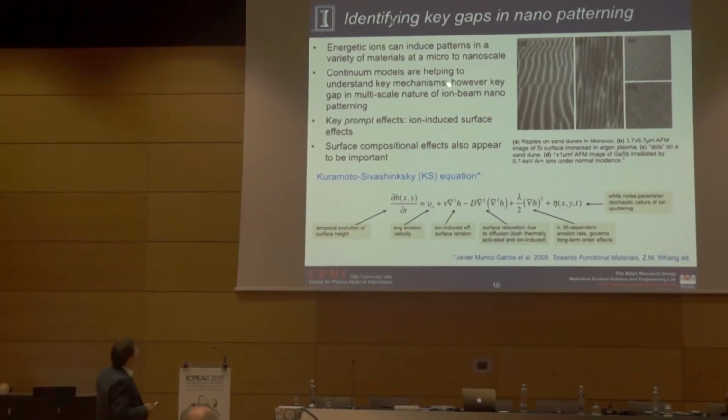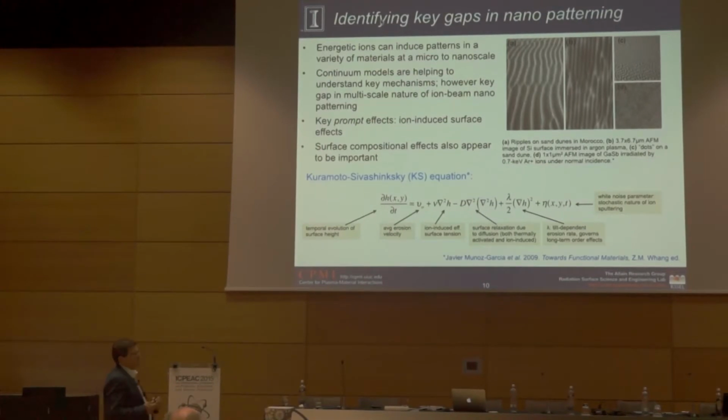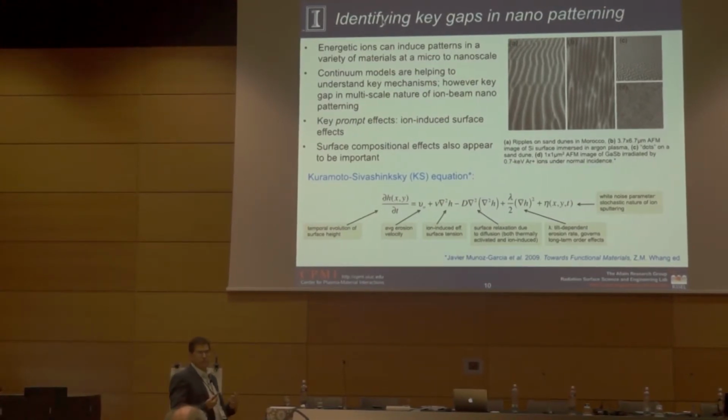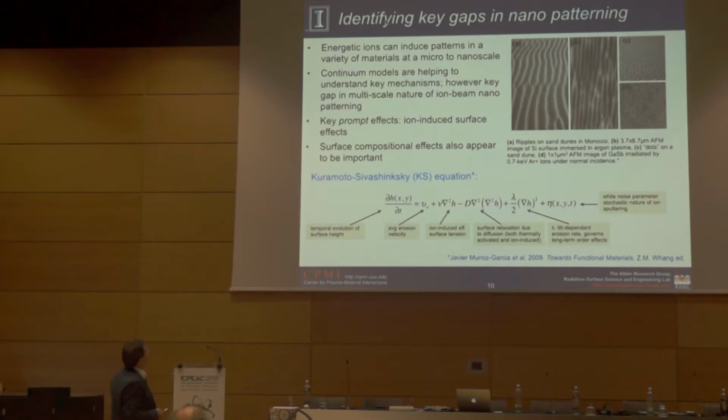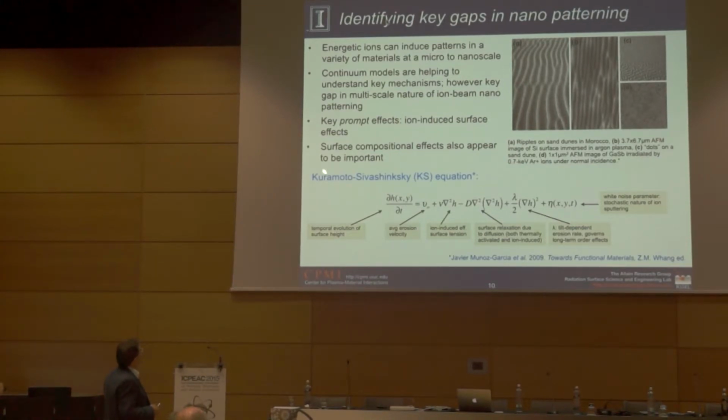Okay? One of the key differences, though, and one of the aspects that are still key questions related to our ability to control these patterns, has a lot to do with an understanding of both the prompt effects, which deal with the ion-induced defect dynamics near the surface, and the relaxation effects, or long-term effects, which is thermal diffusion of atoms as they relax over time on the surface.